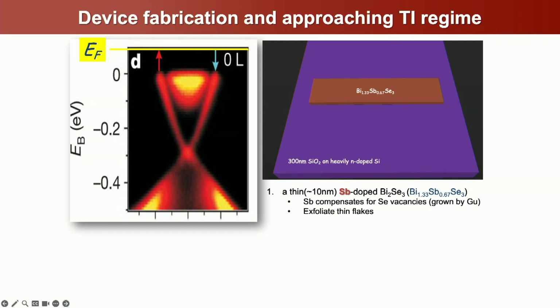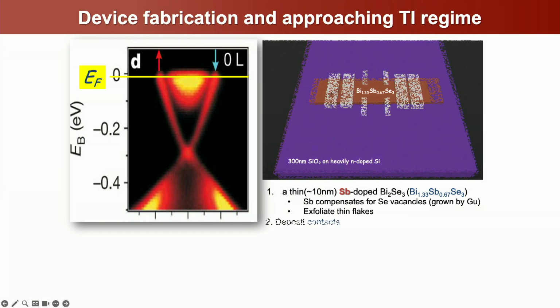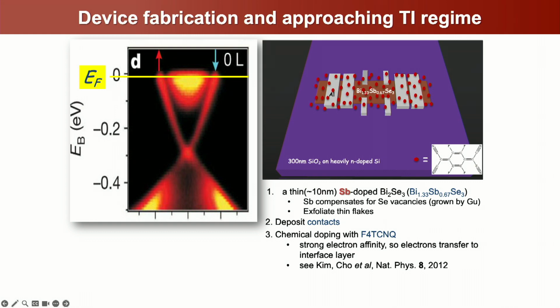The material we use has antimony compensating for selenium vacancies, which also brings down the Fermi energy. We put contacts on it, and then we'll often use what's called chemical doping, which is just a chemical material that has a strong affinity for electrons, and so it basically sucks a lot of electrons off the surface. Because it's sitting right on the surface, it can be more effective than an electrostatic gate. And then it just locks its doping in as you go to lower temperatures. And so it's a very effective way of lowering the Fermi energy in these systems.